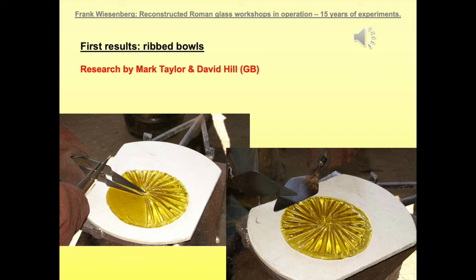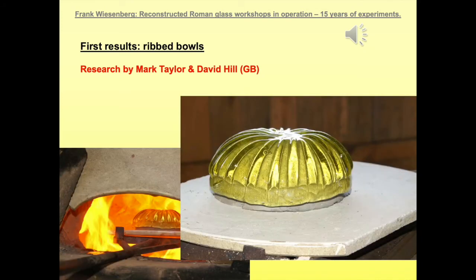For the manufacturing of rib bowls, a blank disc is created on top of a ceramic support with separator. This could be either monochrome glass or mosaic glass, as shown before on the mosaic glass bowl manufacturing. The ribs can be pinched into this flat disc using a pair of pincers. The outer rim can be flattened by using the stonemason's trowels. Also, as before, frequent reheating is required.